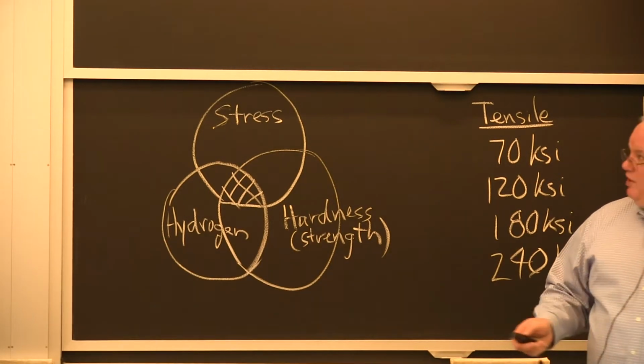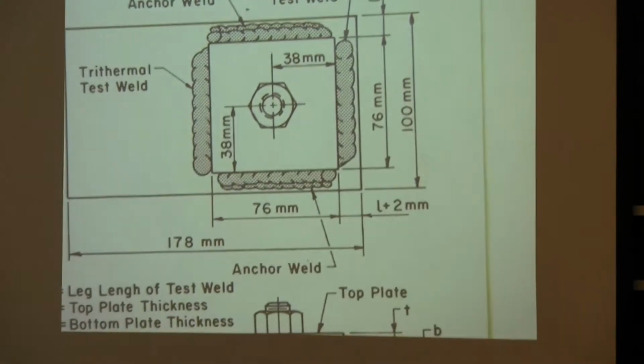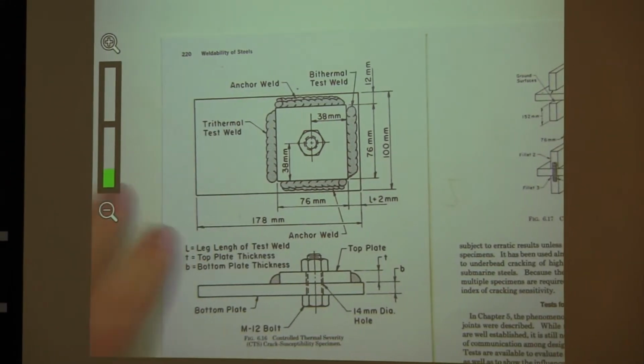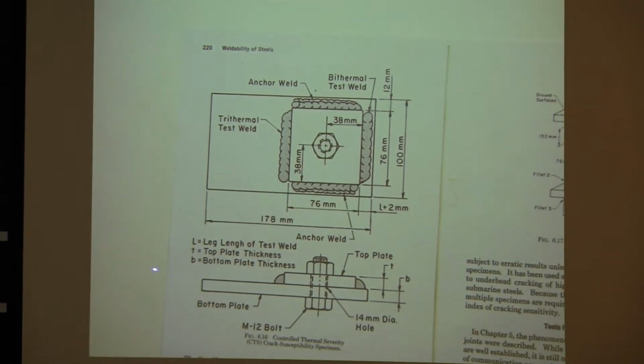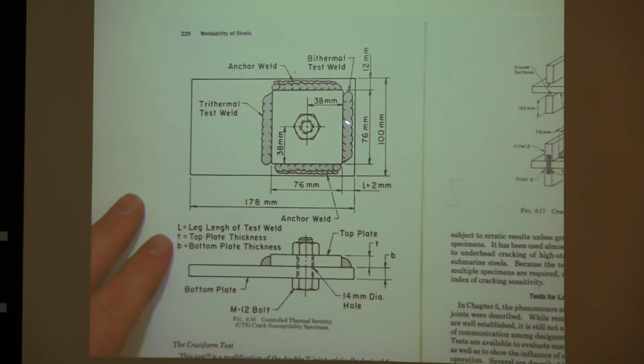And one of the tests that people use is called the cruciform test. If you look in Stout and Doty, which was written back in the 1940s, they would take a plate, put another plate on top, and fillet weld around the edges. They'd bolt them together initially and weld the fillet weld. You bolt it together so it wouldn't bow up on you and turn into a V-shaped joint. So they take a high-strength bolt, bolt it together, and weld it with their electrodes, and then look at it and see if you get a crack.